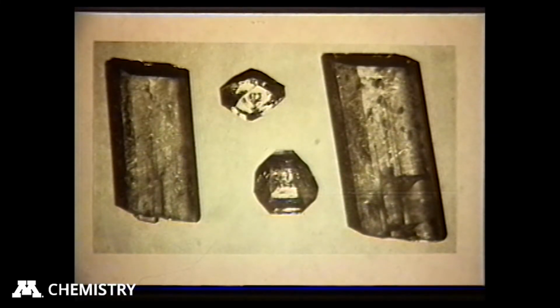And what this actually is a small molecule crystal model of the catalytic triad of the serine proteases. And so what we have here is an imidazolium ion bonded to a picrate and also bonded to a betaine molecule. And the stoichiometric ratio is 2 to 2 to 1, which really isn't critical for our purposes here. But we had no idea that this combination of molecules would form big, high-quality crystals. And apparently these grew very easily. What solvent did you grow these out of, John?